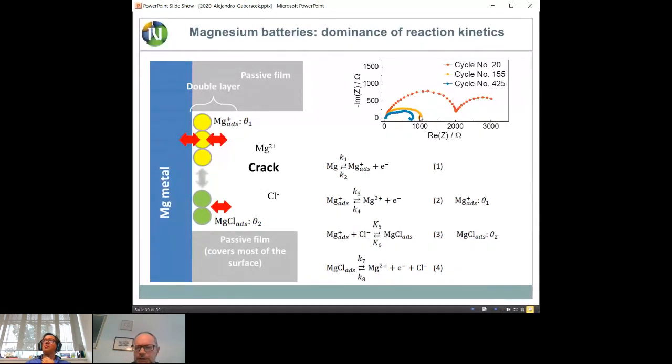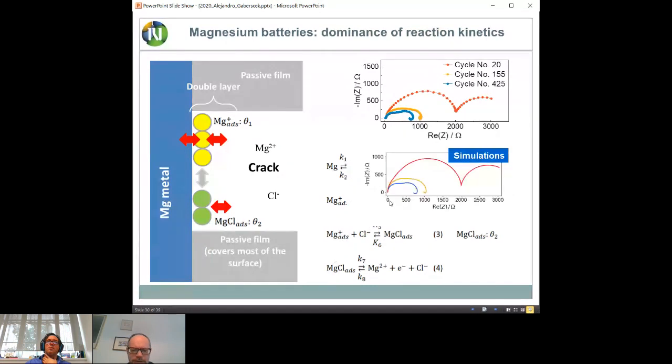And from experience that we have from previous work on corrosion, we know that if you see this kind of spectra here with these loops here, then you would have some adsorption like here. And we figured out a model out of this. So you can calculate this analytically, actually. These are just several kinetic equations together, and you can calculate them. And even a rough analysis shows you all these kinds of shapes.